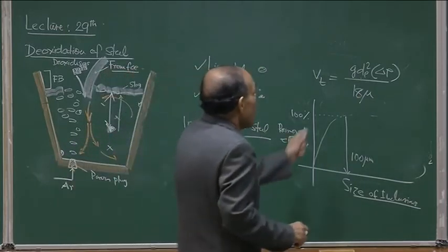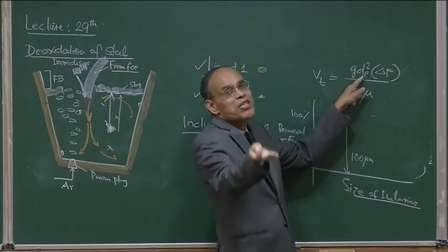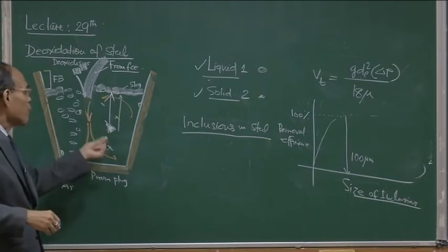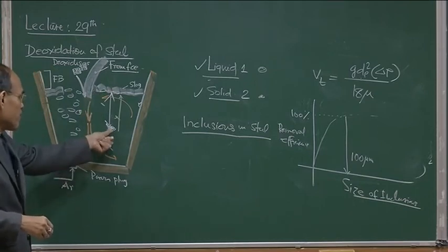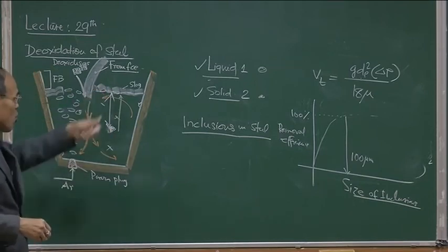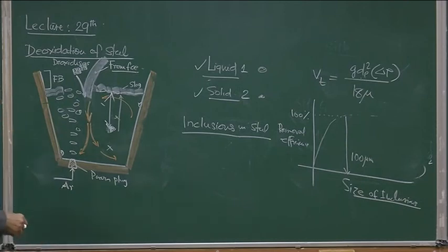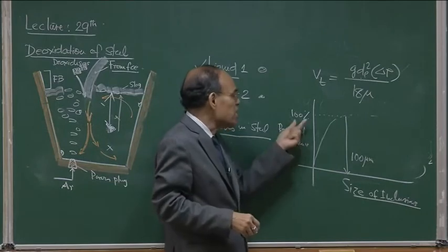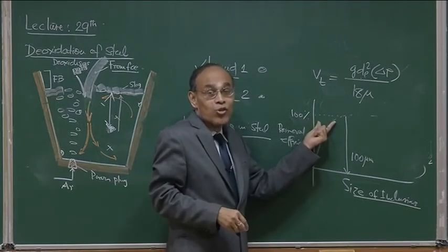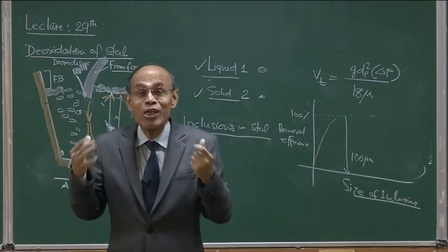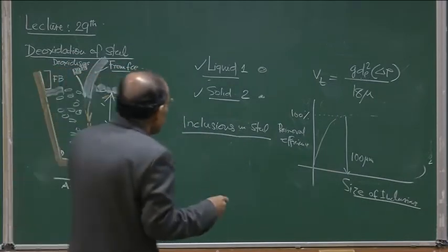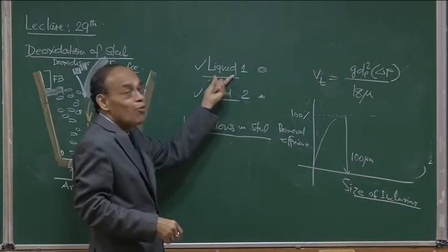Okay. So, 100 micron size particles have sufficiently large terminal rise velocity, and they will float up from the mid bath point, mid depth position to the free surface, or be absorbed by the slag in about 5 minutes, 4 minutes or something like that. So, that is why we see that removal efficiency is nearly 100%. So, that is why we are desperate to get bigger particles. Okay. So, that is why we are desperate to get liquid, but this is not so efficient.